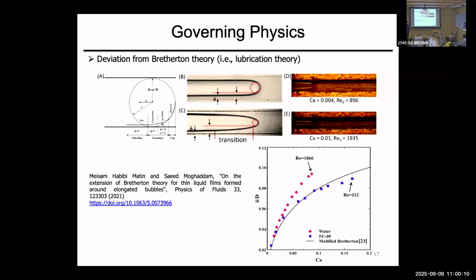So basically, Bretherton assumed a circular profile, and then solved this Landau-Levich problem. And when you start deviating from that, you see that the bubble tip becomes like a bullet, and you deviate from the solution because inertia plays a role that you're not factoring in. So at the lower capillary and low Reynolds number, you can still predict from modified Bretherton, but as soon as your Reynolds number increases and inertia comes in, you can clearly see the deviation.